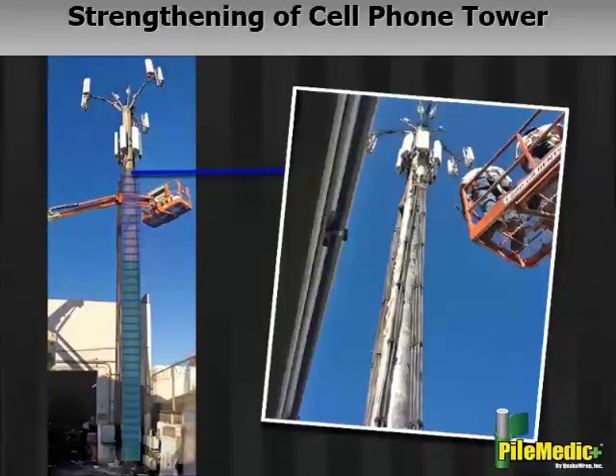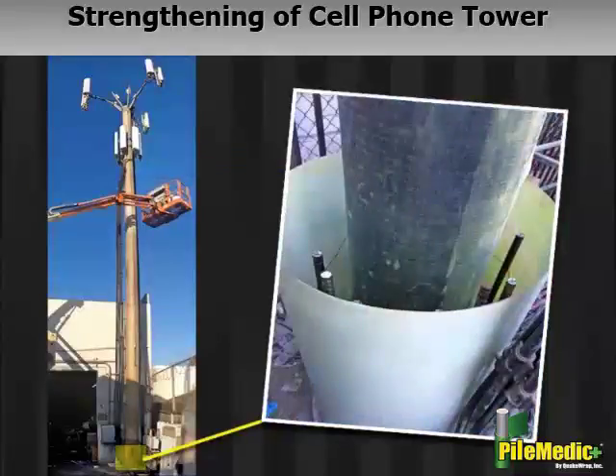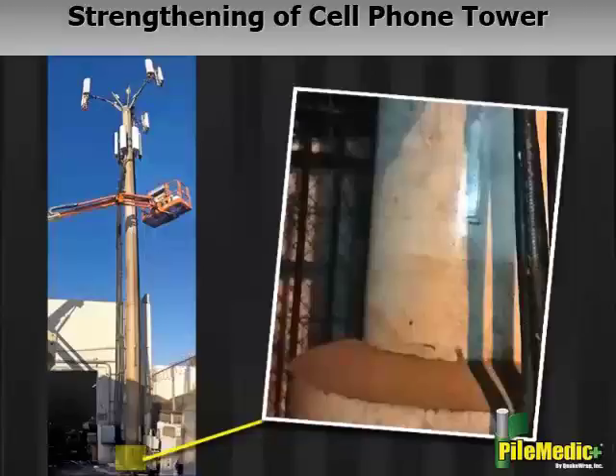5. PileMedic jacket was used to create a reinforcing shell around the lower 4 feet, or 1.2 meters, height of the tower encasing the steel reinforcing bars. The 6-inch, or 150 millimeter, annular space was filled with an expansive non-shrink grout.